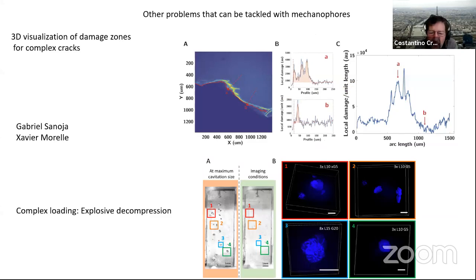Now, I finish with two prospective examples. We are very interested in the technique, not only for fracture in simple networks, but also because you can really have a 3D visualization of damage zones. So right now, Gabriel Sanoja, who is a postdoc working in my group, is working on a crack propagation problem where you can see that the crack is not really going straight. It deviates, it has side cracks. And with post-mortem observation, you can really quantify.